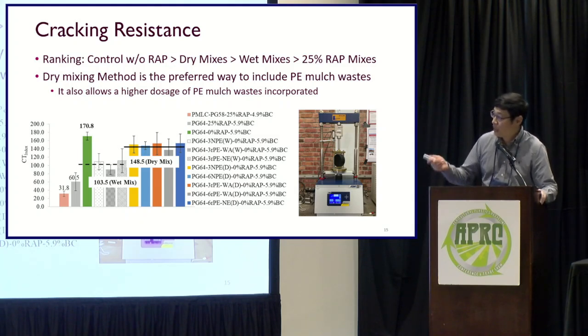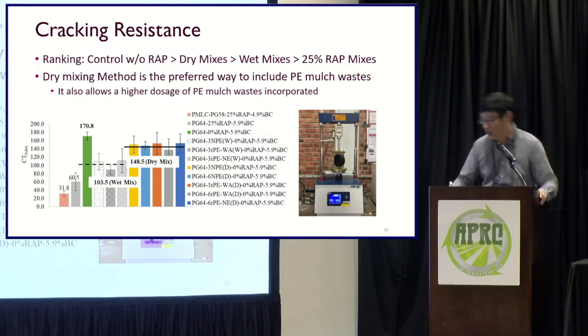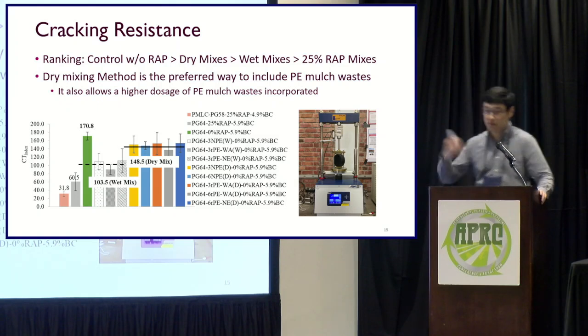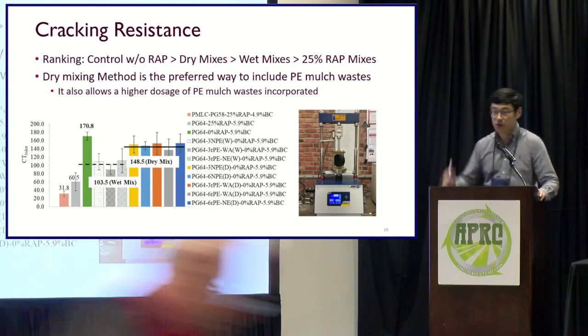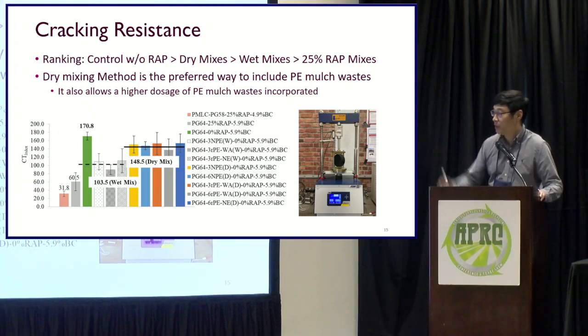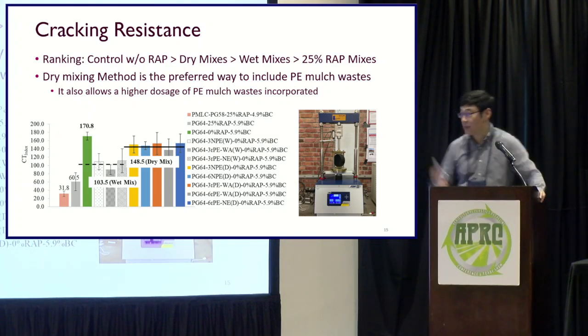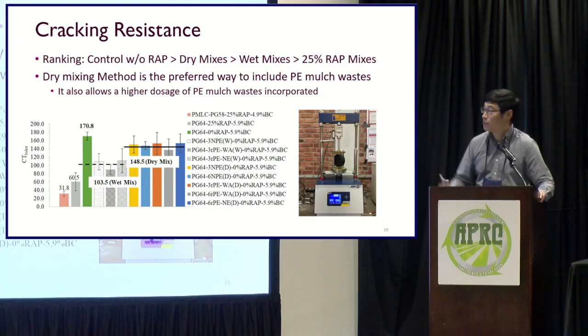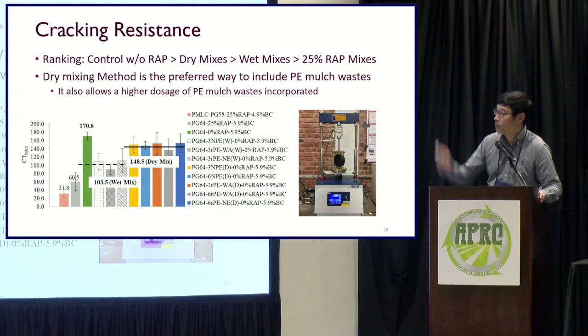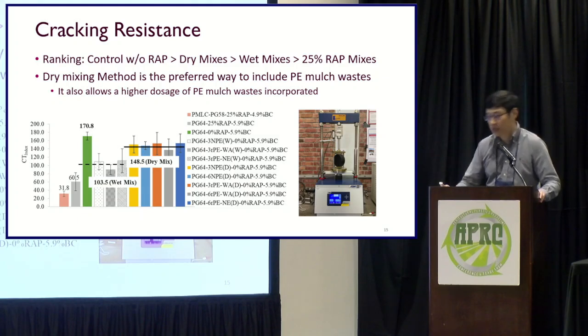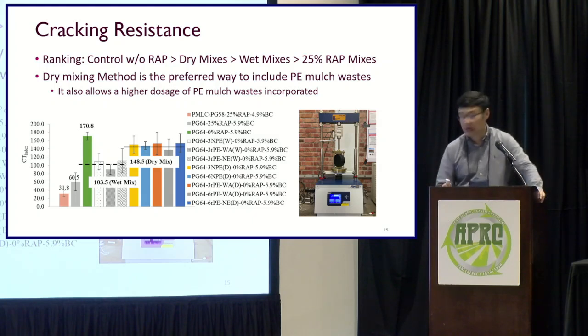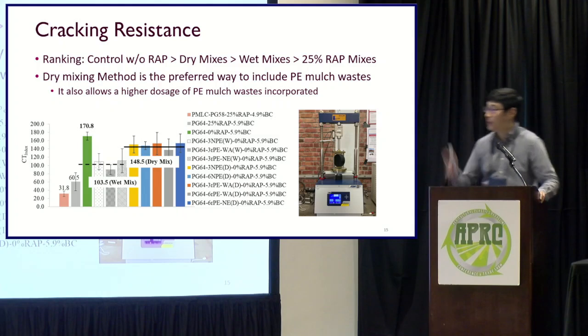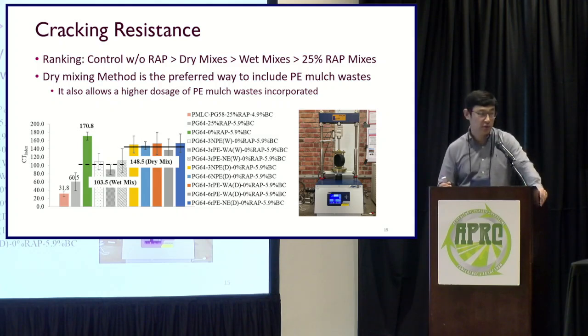So, well, when we use the plastic over there for the wet mixing, it's kind of a decrease to the 103, 104, but still it's much more than 50, the threshold value, which is good. And for the dry mixing, it's 140, 148 on average. So it has a good cracking resistance. So we have the cracking ranking over there, and the conclusion is the dry mixing method is a preferred way to include the PE mulch waste in the asphalt. And also it allows a higher percentage at 6%. And this is also the preferred way for the paving contractor to include the additives into the mix, the dry mixing method.